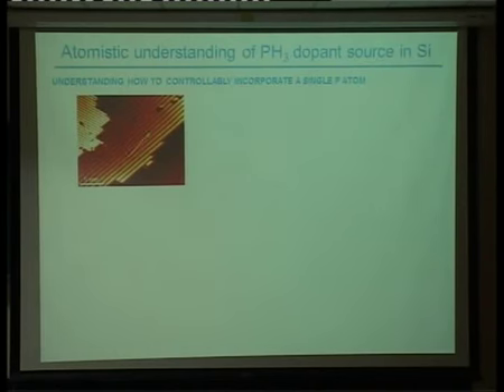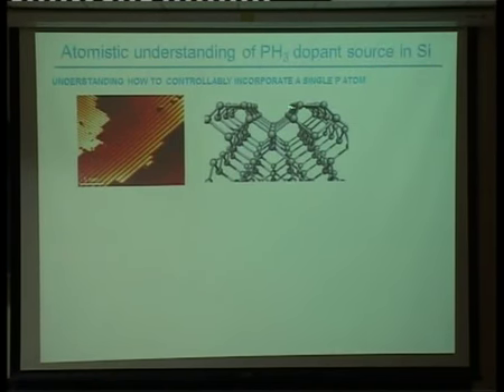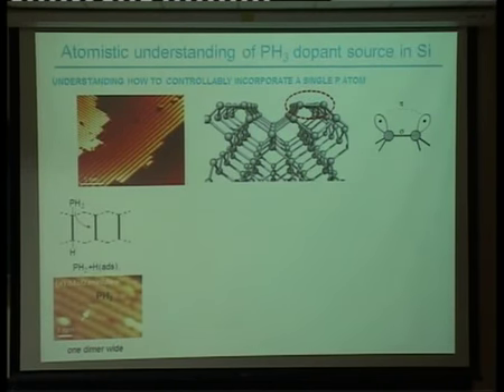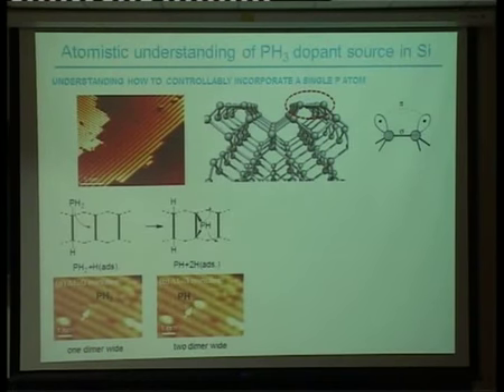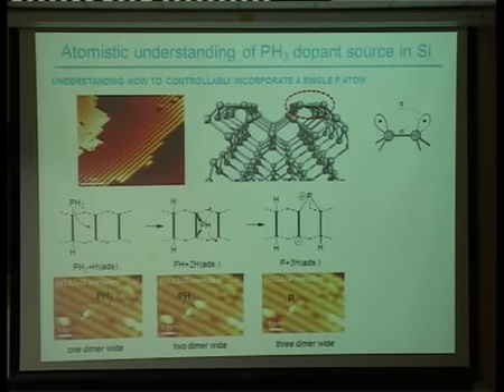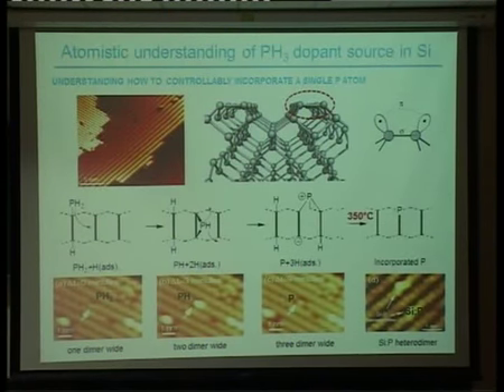This is the silicon 100 surface that we use. These are rows of silicon atoms. If you look at the surface, we get these silicon dimer structures where there's this strong covalent bond that I talked about before, and these 2 dangling bond states of the surface. If we just look at what happens to phosphine gas, this is going to bring our phosphorus atom in. We see that phosphine likes to dissociate on the surface until eventually it sits in an end-bridge site, and we heat it up, and it goes in and forms a silicon-phosphorus heterodimer.